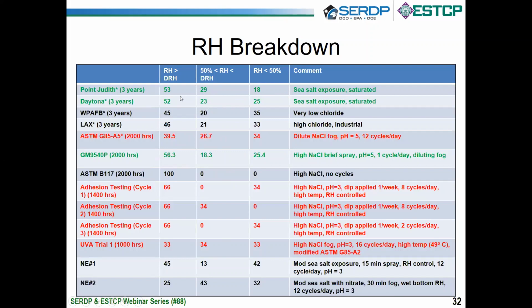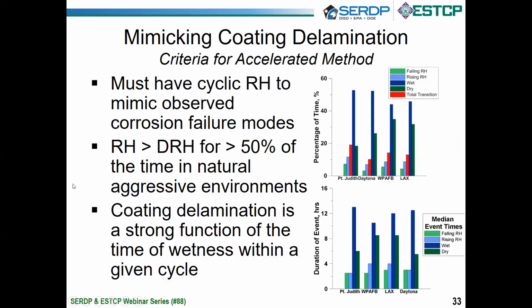These are marked as green because this is what you see as aggressive corrosion outside. And you can see our laboratory tests, these are marked in red. Some of these things are really aggressive, and you saw some of the images from that. So just to summarize, we know that we've got to have cyclic humidity. If we don't have it, we don't fire off these separate modes that we see in the real world, like I showed you in Point Judith. And the other thing that we know from the real world tests is if you want aggressive environments, you've got to be above 50% relative humidity, or above the deliquescence point 50% of the time.